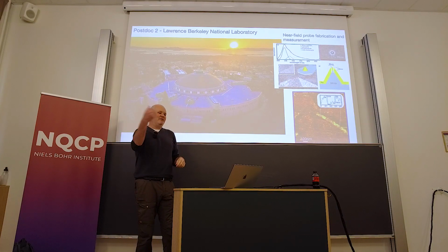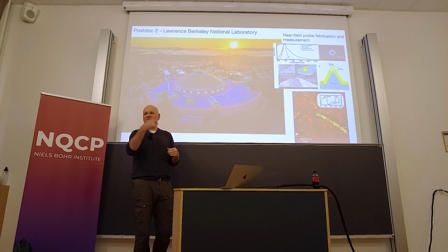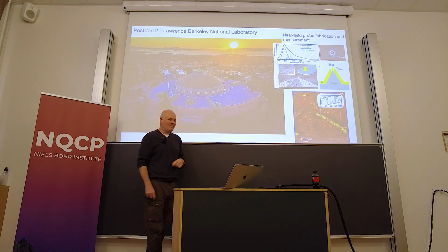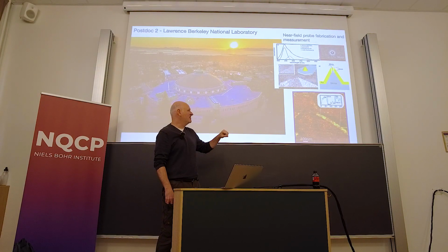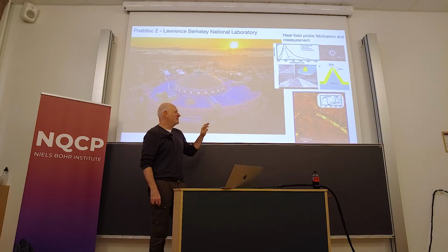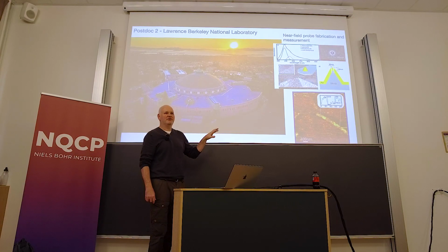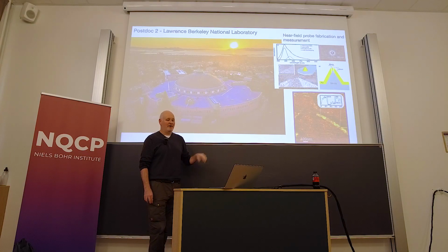And then you can shine light through the back and actually take Raman spectra through the silicon nitride tip. And so here's just one example of a single carbon nanotube where we get something on the order of 20-ish nanometer resolution, optical resolution with Raman.